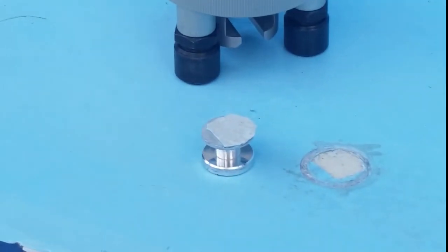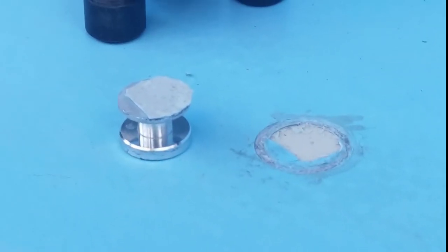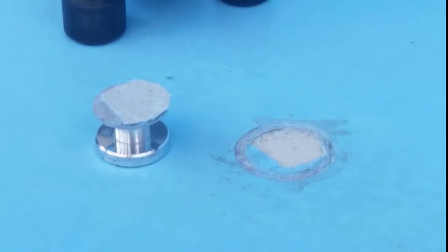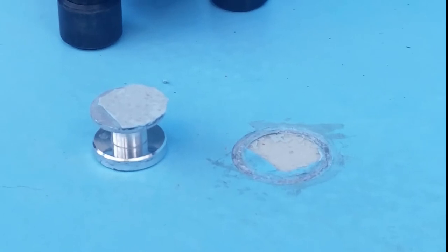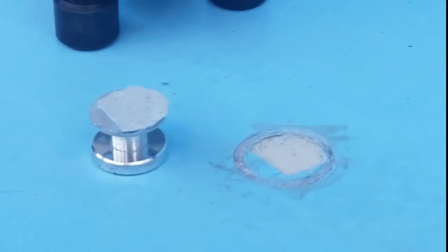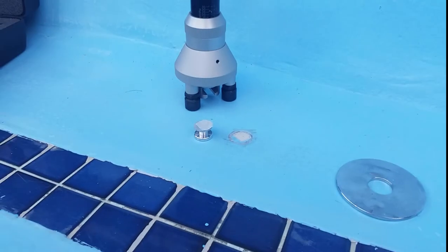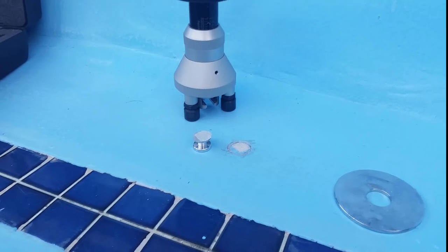Now this is very high. On normal concrete surfaces, it is generally specified that a minimum bond strength of 170 psi should be achieved, and we have reached 400 psi on this coating, which can be attributed to the specialized primer that we use, the concrete epoxy primer, and then a very high level top coat epoxy formulation.